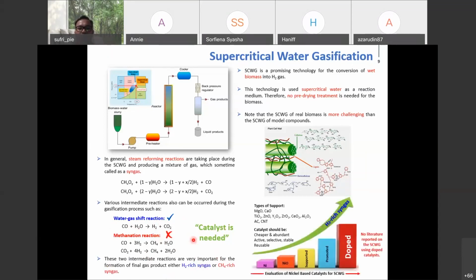Since I'm interested in hydrogen gas, from the literature, the nickel-based catalyst is widely reported as the heterogeneous catalyst to produce hydrogen. The nickel-based catalyst can be in the form of nickel metal or nickel oxide. This is the active component and can be supported onto different types of support, for example alkaline metal oxide, transition metal oxide, or, for some researchers, carbon-based support such as activated carbon and CNT, carbon nanotube.